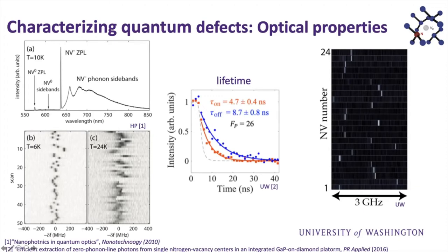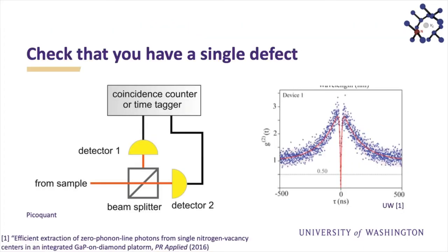So these are just on single defects. The other thing to note is that if you look at an ensemble of them, each one of these is a different NV center in a sample, and these NV centers were created by implantation and annealing. So each one is emitting at a slightly different frequency. And so we need a way that we can match all of these frequencies as well. Okay. So these are the types of measurements that we do.